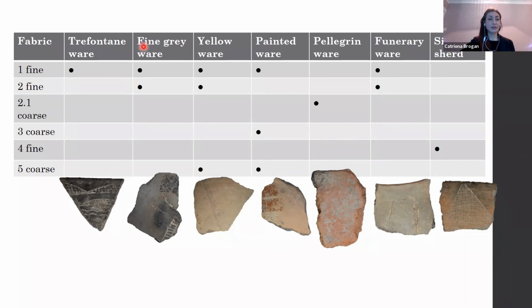Then we have a sort of fine grey ware, and this is a very common fabric that appears in Sebouge. We then have this fine yellow ware, which tends to have a very yellow surface and is often quite highly decorated. Then we get the painted ware, which has a thick plaster-like surface, and it's painted. This is the first evidence of painted decoration that we have in Maltese pottery.